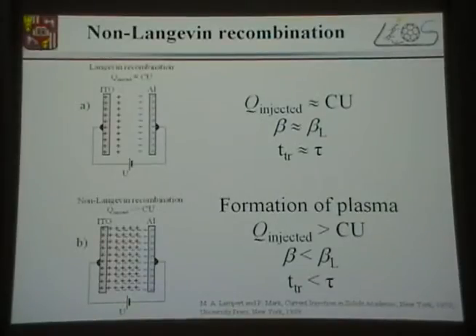So reduced recombination, and you can read a lot about this in Lampert and Mark's book, but the basic thing is here. I compare double injection with Langevin recombination, so we inject electrons and holes, that's typical of OLED. And the efficient recombiners emit light, and it's very efficient injection and recombination. Whereas in non-Langevin recombination, like in efficient P3HT:PCBM solar cells, we have charge carrier accumulation in the film. And this high charge carrier concentration gives us the high injection current levels. That's why the injection current is very strong, that's how it's explained.